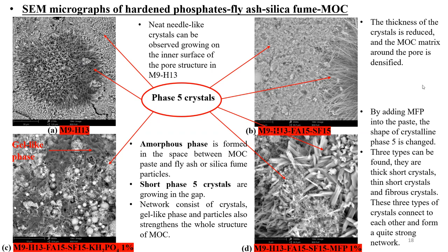So we can also see the needle-like crystals, but the needle-like crystals this time is actually thinner and longer. So the thickness of the crystals is reduced and the MOC matrix around the pore is densified. Then for C and D, so these are achieved a really good water resistant for both compression and for flexural.